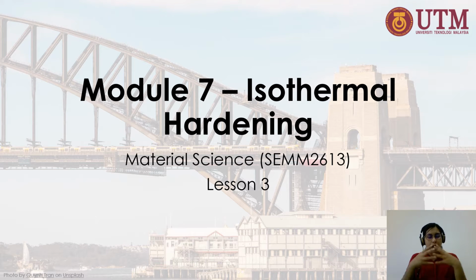So in isothermal hardening, let us now consider what product or what microstructure will be formed for this eutectoid steel. For example, when we rapidly cool it to a temperature below the eutectoid temperature, but not to room temperature. So let's say the eutectoid temperature is 727. We rapidly cool it to 700 straight away, and then we hold it for a certain period of time and let it isothermally transform. What kind of microstructure will be formed? This is what we call isothermal hardening.